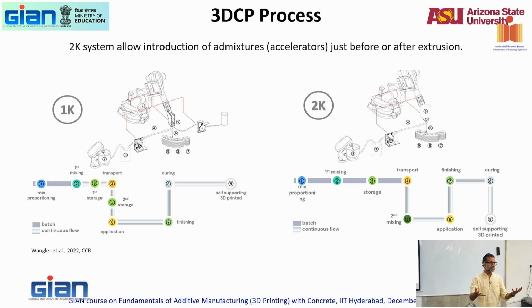You extrude that one material. Now we have 2K systems that will allow you addition of accelerators or whatever admixtures just before the nozzle. Right? So why do you need that? You want it to be extrudable. For that, you want a low enough yield stress so that it's extrudable, but then you add an accelerating admixture at the tip of the extruder nozzle so that when it comes out, it'll become quickly buildable. The yield stress goes up because the accelerator accelerates cement hydration.